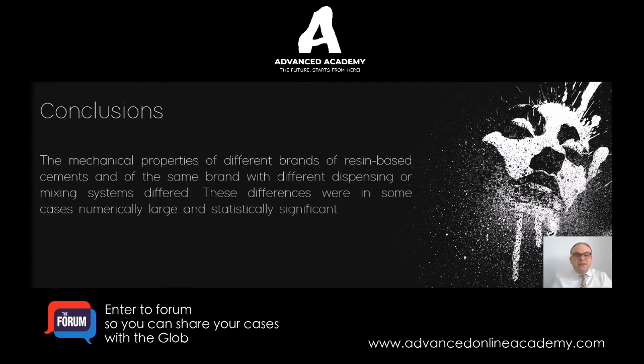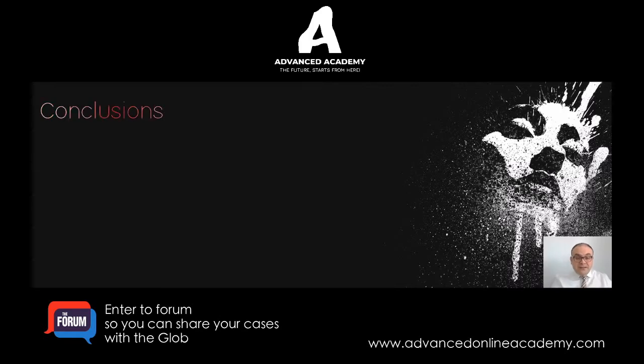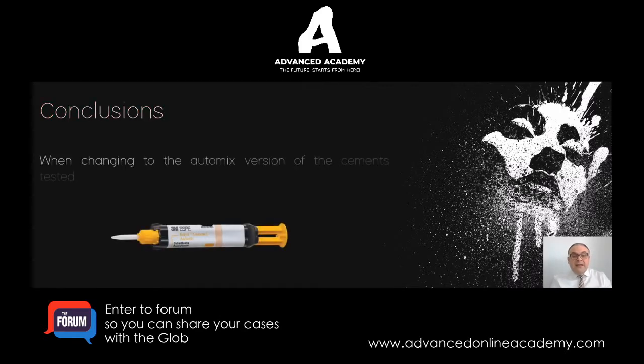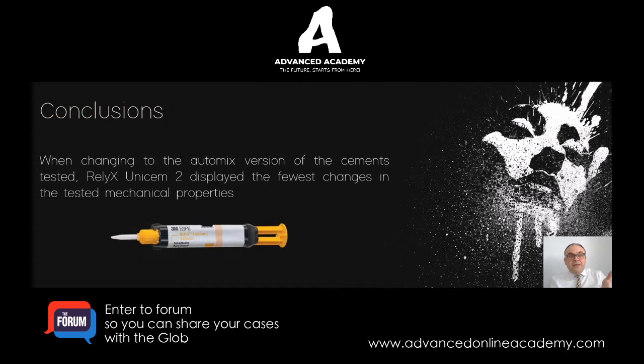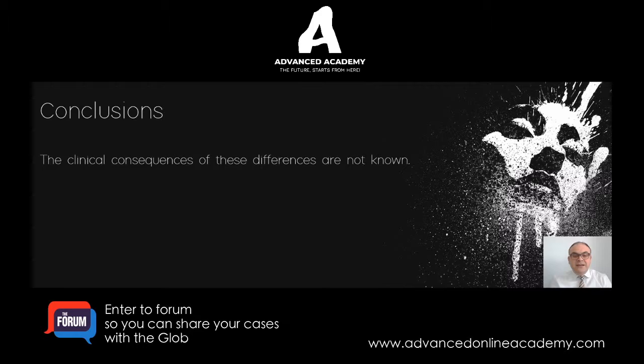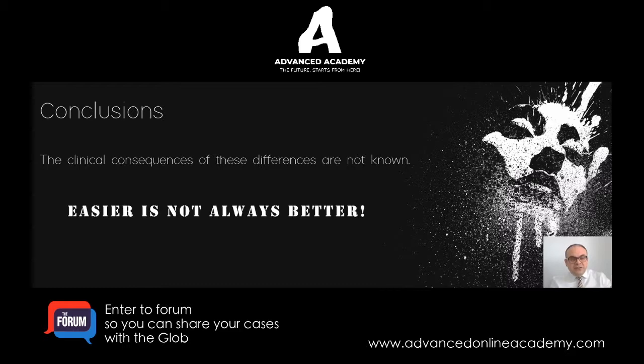The conclusion was that the mechanical properties of these resin-based cements are different based on their way of dispensing, and the only system that we saw was very consistent when changing from a clicker to an auto mix was RelyX Unicem. It didn't really change in its properties that much, so kudos to 3M. How that's going to affect clinically is really unknown, but the ultimate conclusion is that easier is not always better.